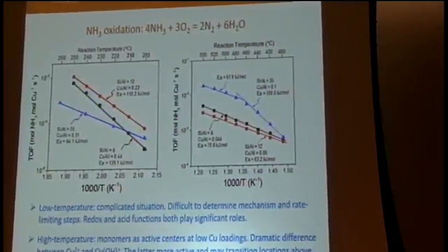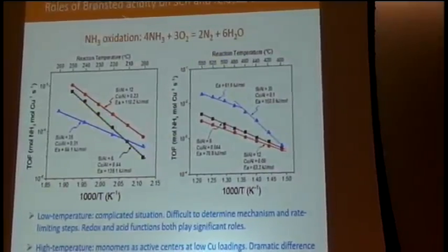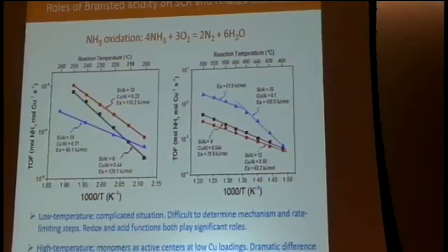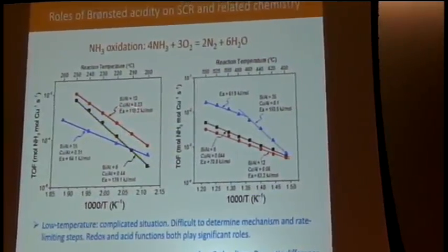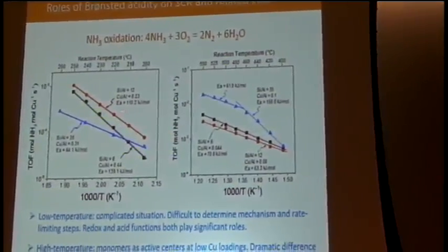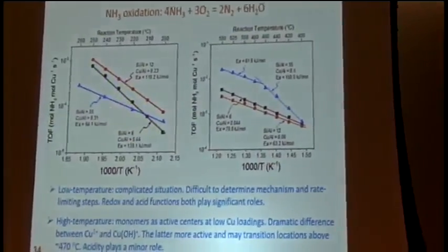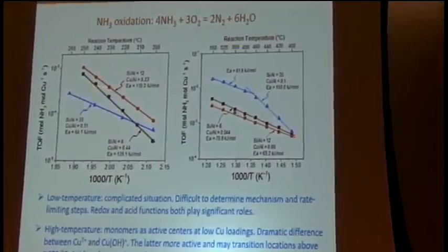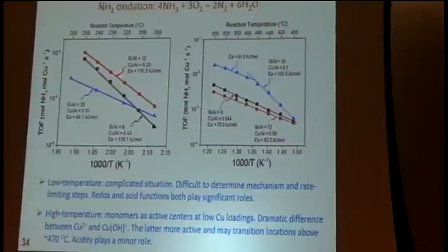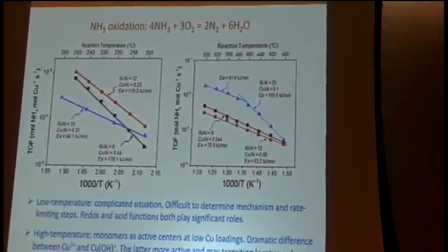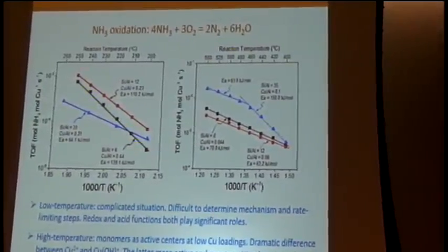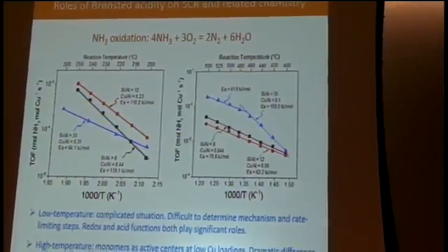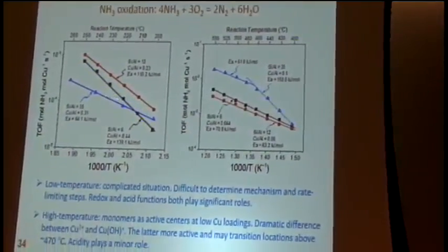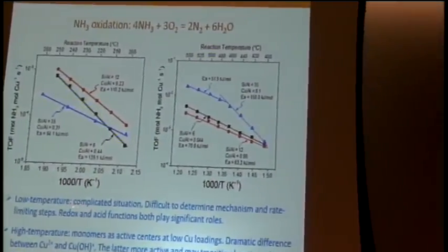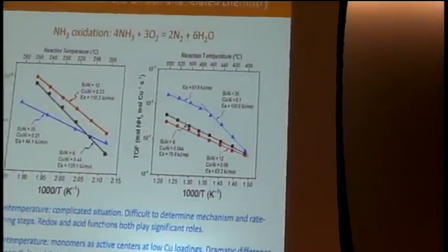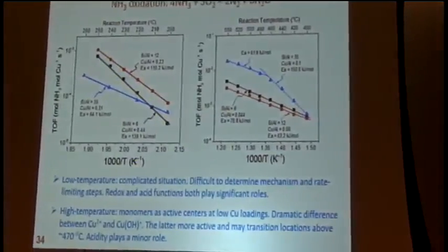And the situation is much more complicated for ammonia oxidation. For ammonia oxidation, we do both low and high temperature reactions on samples with copper loadings that we believe are fair to compare. In the low temperature regime, the situation is really complicated. We know from these Arrhenius plots that the activation energies on different catalysts are so different, and the reaction rates cross into each other. Therefore, we are still not sure we really understand this, but probably we can conclude that the redox and acid functions both play significant roles to cause this complexity.